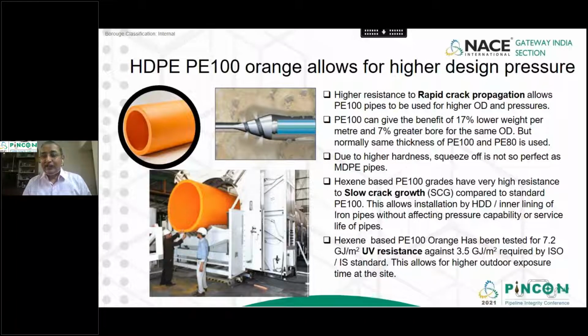PE100 can give the benefit of 17% lower weight per meter and 7% greater bore if used with reduced dimension for the same service pressure. But normally the same thickness of PE80 and PE100 is used.